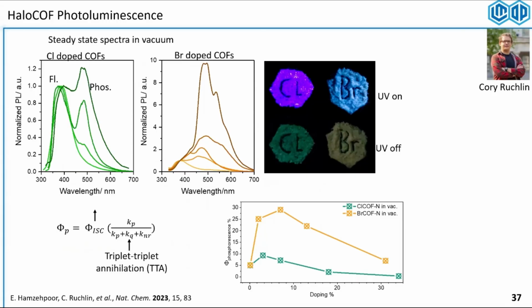Well, they were phosphorescent. We could see clearly that the more chlorine we add to the system, the more phosphorescence starts to appear. And this is much more pronounced in the case of bromine, because of course it's a heavier atom, the intersystem crossing grows faster in the system. But one thing that was unexpected for us, maybe a little bit expected, was that originally the more we dope, the more phosphorescence we get. But then at some point, of course, we're generating more triplet excited states. The phosphorescent quantum yield starts to decrease quickly. So that brought us back to this idea of triplet annihilation.